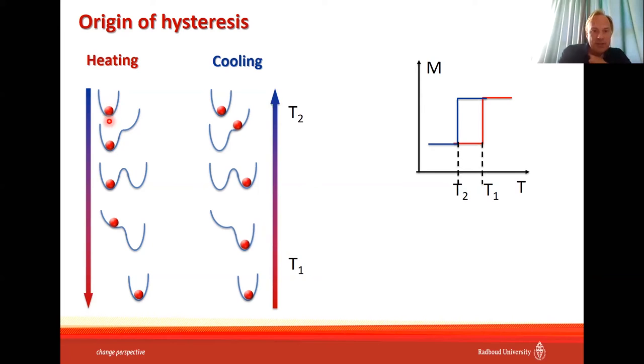Then you increase temperature and change the profile of the thermodynamic potential. Around the phase transition temperature, you have coexistence of phases. It means there will be two minima of the thermodynamic potential, so the system can be in either one state or another. In principle, these states can coexist. But then if you increase temperature, starting from one minimum, this minimum becomes less and less favorable energetically and eventually disappears, such that the system should drop into the other minimum. So if you start from one minimum and slowly increase temperature, the system will drop into the other minimum at one temperature, let's call it T1. If you now decrease temperature, the system will stay in this new minimum and will drop into the other one at a lower temperature, T2. That's why you have temperature hysteresis in the measurements of magnetization as a function of temperature.